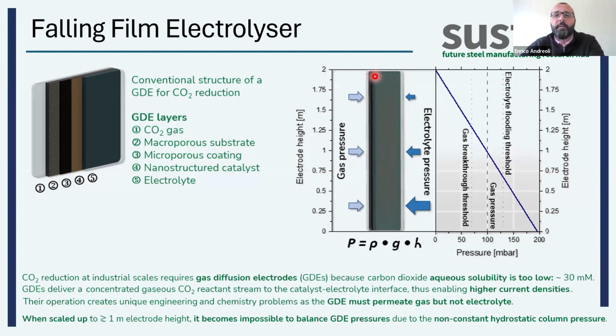Now, if we do this on very tall electrolyzers, the water on this side creates a pressure due to its own weight and density, and the pressure differentials that we create across this membrane create very big issues from an operational point of view, because the pressure is higher at the bottom than at the top, and this makes the process unworkable. The use of that cloth I told you before is actually the solution to this problem, to equalize the pressure and to be able to do electrolysis on a very large size, okay? Something that is not being tackled at the moment.